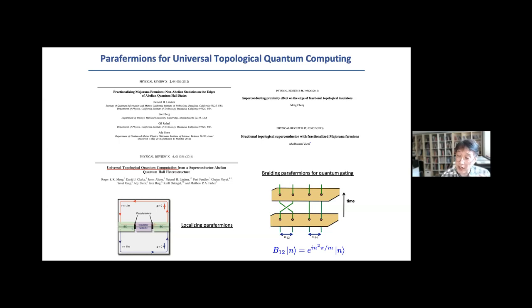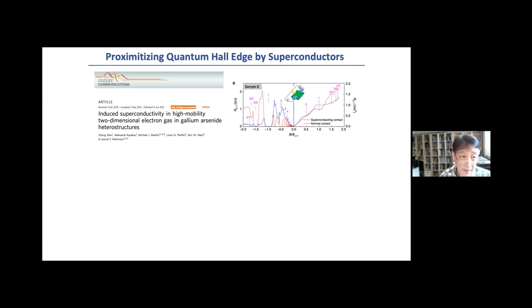In particular, to combine superconductivity with the fractional quantum Hall effect, you need to figure out how to make good contact with a superconductor that has a very high Hc2, such that the superconductivity can survive within the reasonable magnetic field one can set up to realize the fractional quantum Hall effect. One notable example was done by Leonid Rokhinson's group at Purdue in 2014. They used a gallium arsenide 2DEG combined with a niobium superconductor, where the fractional quantum Hall effect sets in at a few Tesla, well below the Hc2 of niobium, and they demonstrated that they can use a superconducting contact to measure the fractional quantum Hall effect.